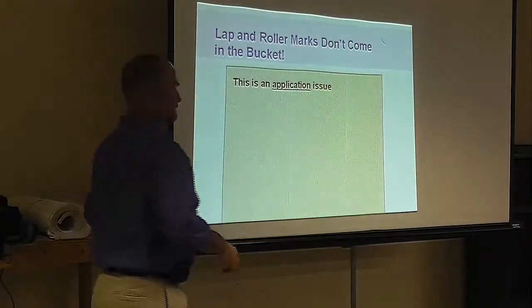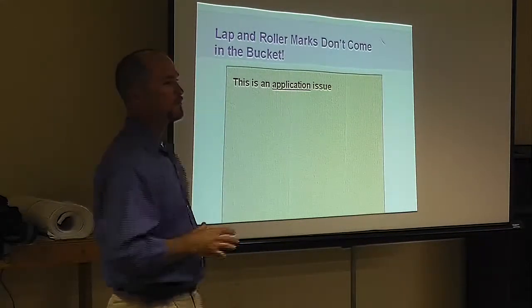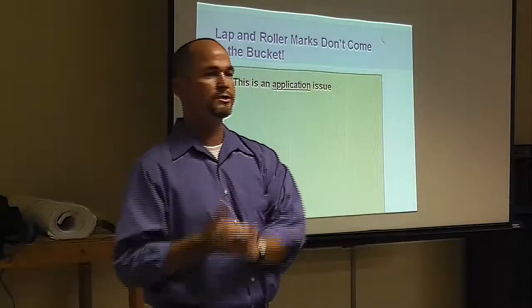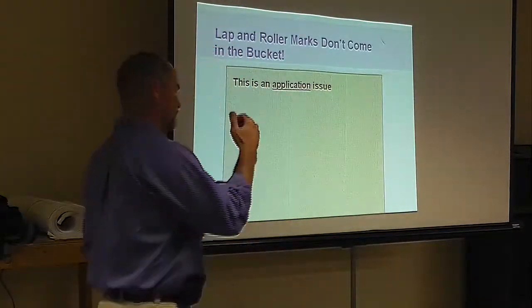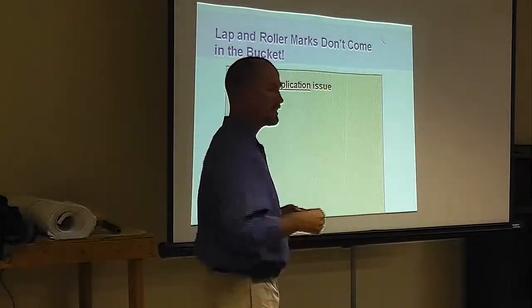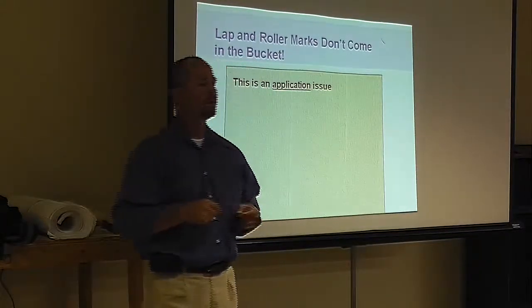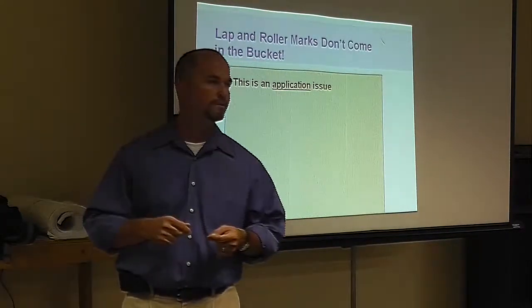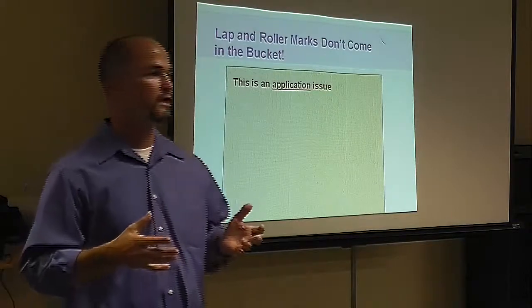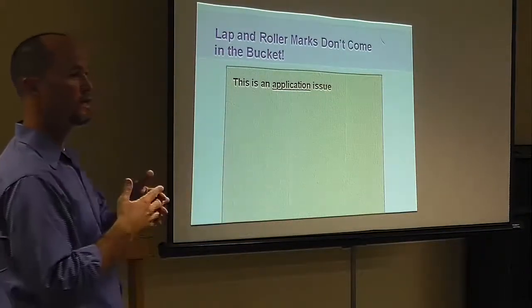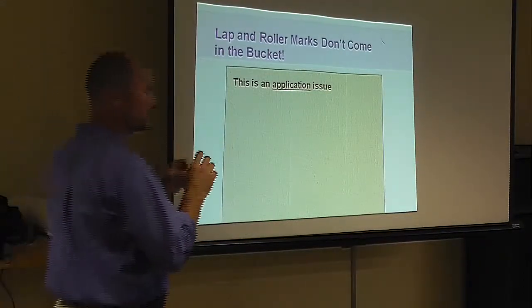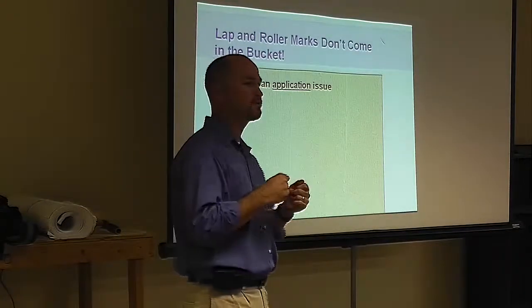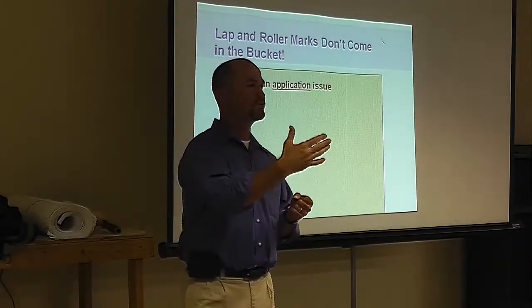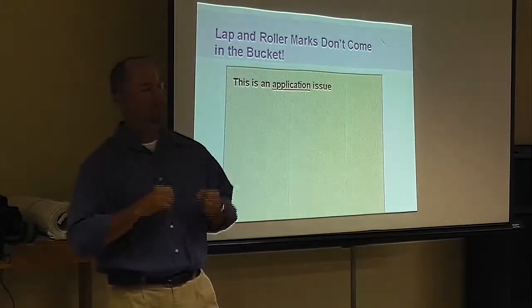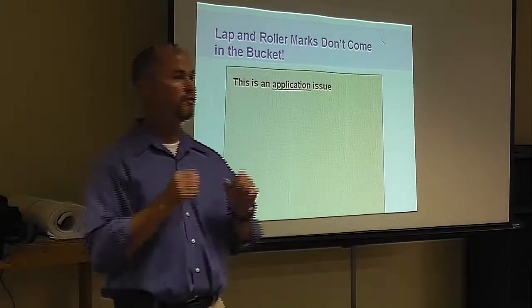Also temperature. If it's really hot, they shouldn't be coating the building. I had a project with GDA not too long ago, and we were going to do it at night, and it was 7:30 at night. I ran a temperature gun on that wall, and it was 150 degrees still. That's too hot to throw a coating on it, because it doesn't let it coalesce. It makes it where you get these little craters in it, so they need to take that into consideration when doing wall coating jobs. Do it in the shade or schedule it to do it at night, but when a building's really hot, coating doesn't stick as well.